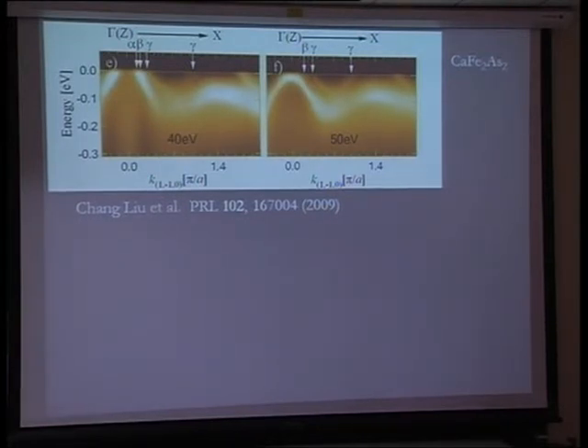So you can see that if you change the photon energy, that means you are changing the kz vector, that's the thing which I mentioned earlier. So what you are seeing is that this alpha band, which was crossing the Fermi level, actually doesn't cross the Fermi level anymore. The beta and gamma, of course, they cross. So this shows that these bands actually have a kz dependence. So we know that this 122 iron arsenide family which shows superconductivity is effectively having a 2D kind of electronic structure.